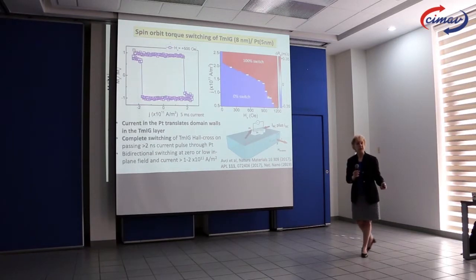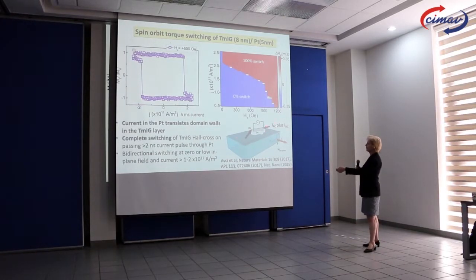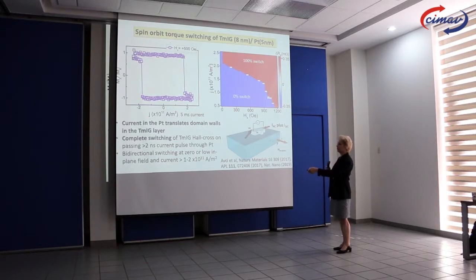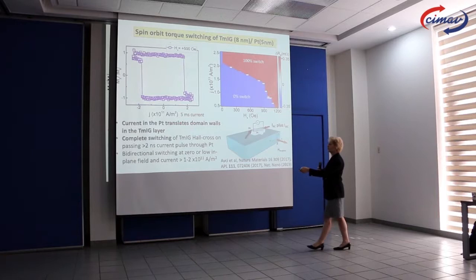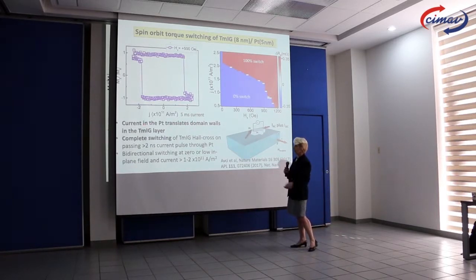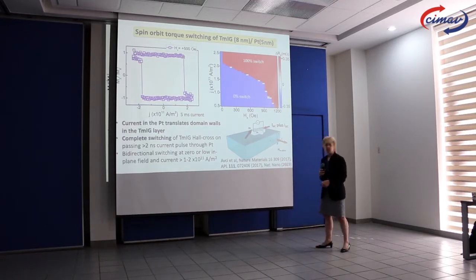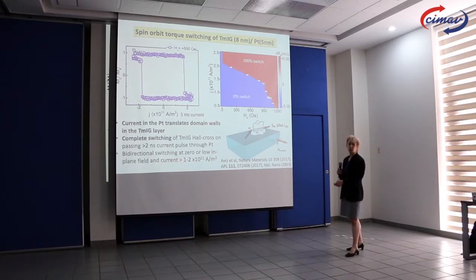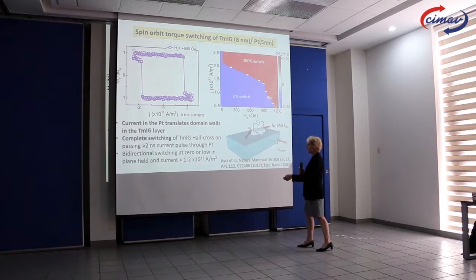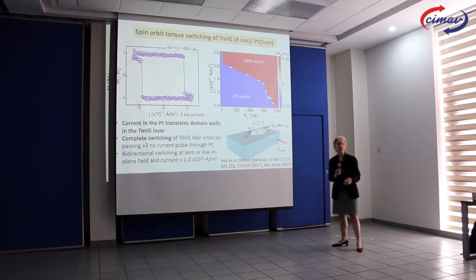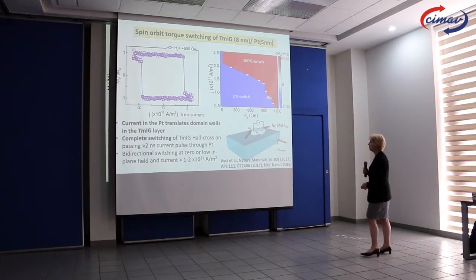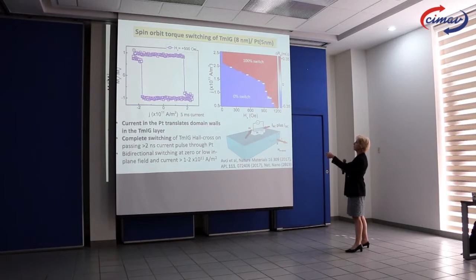Now, what about affecting its magnetization? If we flow a current through the platinum and that spin orbit torque interacts with the garnet, we can actually switch the garnet. So for particular current density, what we're doing is actually translating domain walls in the garnet using the spin current from the platinum. And this can be very successful. We can switch the whole garnet with a 2 nanosecond current pulse. And the currents can be very small. Well, they are small, it doesn't look small, but 10 to the 11 amps per square meter is the current density in the platinum. It's not very many milliamps because the platinum is very thin. So we can have a regime where it switches and a regime where it doesn't switch, depending on how much field and how much current we've got.